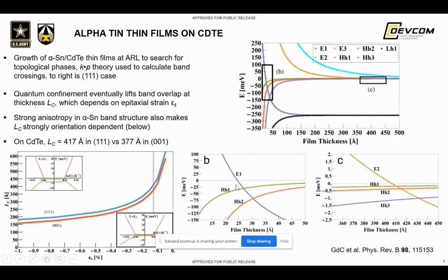I'd like to emphasize in this plot here that we can actually go to very thin layers, you can actually go to complete removal of the band structure inversion, and you can go from a 2D topological insulator to a trivial 2D material if you go to very thin thicknesses. The only problem is that experimentally realizing or seeing this transition is very difficult because you have to move your Fermi level between these heavy hole bands, which makes it very difficult to realize experimentally in transport measurements, for instance.